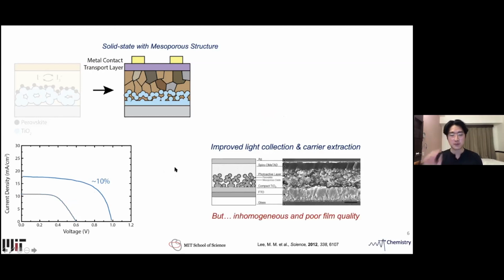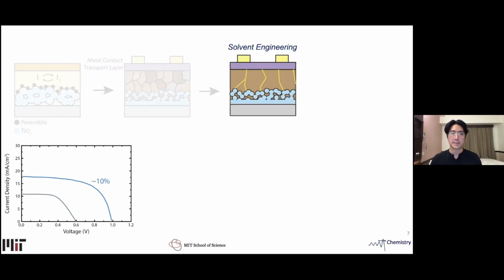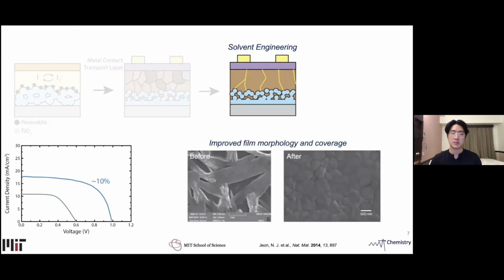However, they suffered from inhomogeneity in films and also poor film quality, such as pinholes or incomplete coverage. To overcome this, a method called solvent engineering was developed, where the perovskite crystallite was precipitated in situ during fabrication using non-solvents. This resulted in improved film morphology and coverage, as shown by this SEM image below. And with that, the efficiency rose to about 15%.